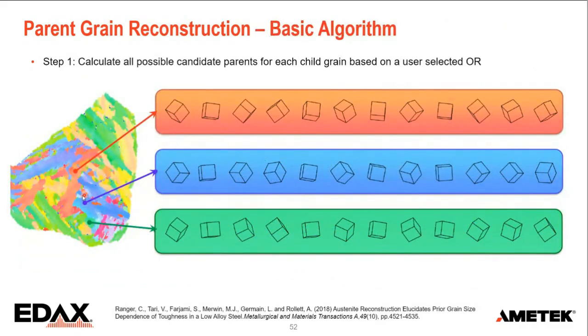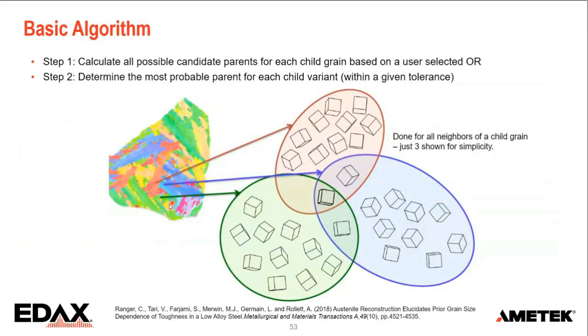So how does that work? Basic algorithm: we look at all the individual lamellae. In each lamella, in each orientation, we identify what all the possible parent grains are. And then we can look at neighboring grains, and we just compare these clusters of possible parents to see if there's one that they all share. Then that's most likely to be the parent that produced these child grains.